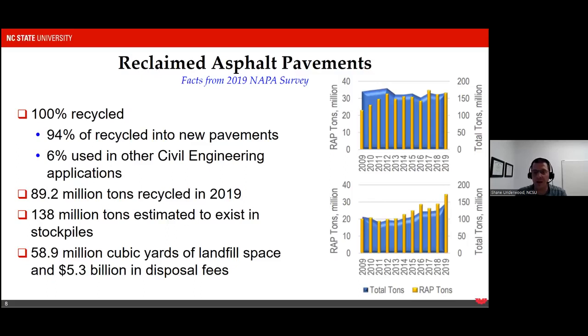You'll see on the graphs on the right side that the tons of RAP materials have increased over time. So we continue to use more tonnage, at least, of RAP materials, and that's been the case for the last 10 or 15 years. Part of the reason that the tonnage of RAP materials increases has to do with the fact that we have improved some of the engineering capability with these RAP materials. As states gain more experience with them, they're more likely to use RAP. And so we've got a lot of increased experience, and with that comes increased usage rates.